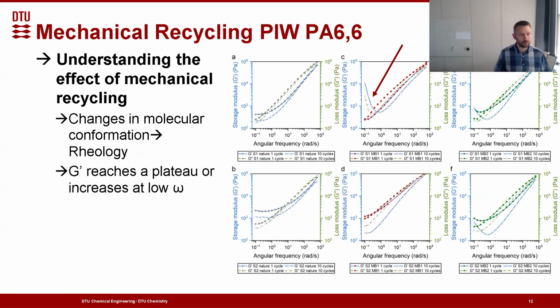If we, on the other hand, look a bit more at the melt flow properties of these systems, we noticed one thing in these samples that we did not expect, and that was that some of the samples, like the one you can see with the red arrow here, change their properties as we're measuring them. So we run rheology tests, in this case a frequency sweep, on the different compounds. We can also see that the different compounds react very, very differently. And what we're observing in this case for the red arrow is actually cross-linking taking place for this specific combination of master batches and suppliers.